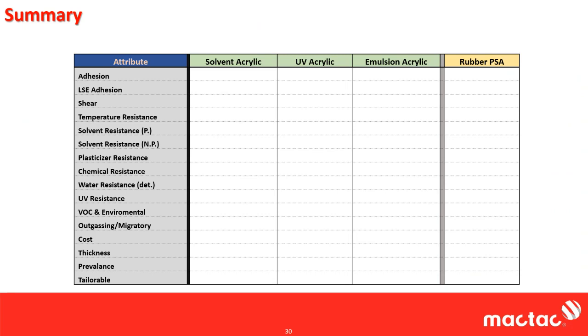So the first thing's going to be adhesion. Your solvent and UV acrylics are going to be pretty high adhesion. And this scale goes from 4 pluses to 1 negative. So again, 10 pounds for solvent acrylic and UV acrylic, pretty high. Emulsions usually top out 5 or 6 pounds for a comparable coat weight. And then actually rubbers, nothing's going to touch rubber in terms of adhesion. Rubbers are always going to be your highest adhesion options. They'll get 15, 17 pounds at the same coat weight.